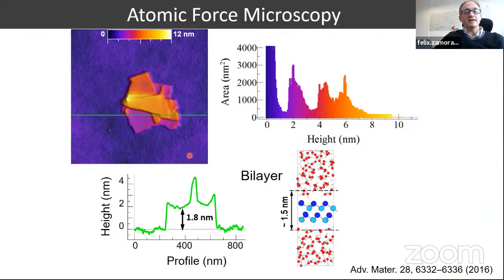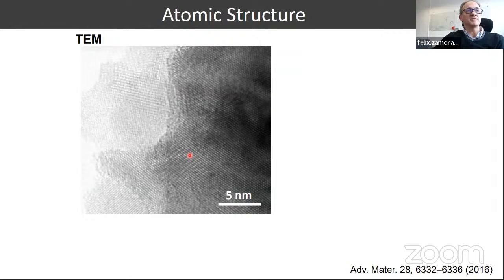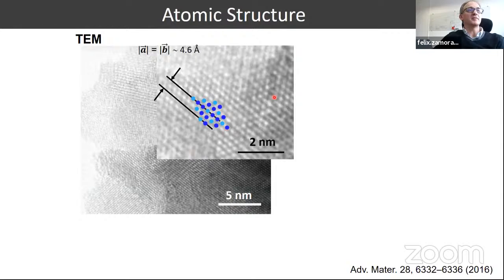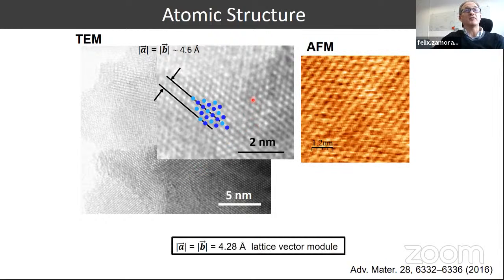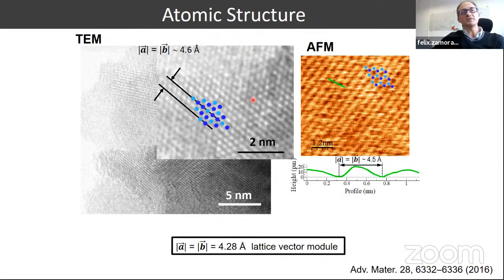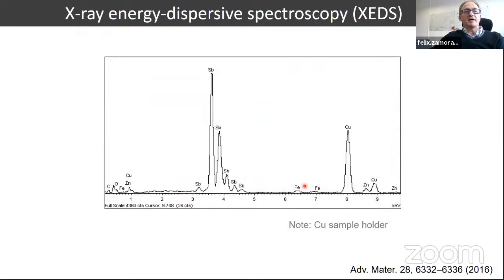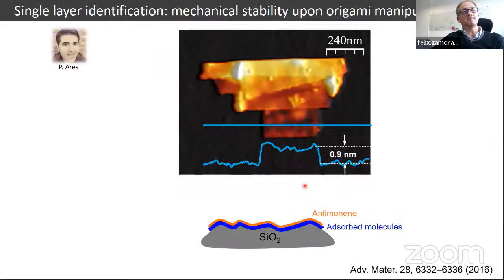Additional characterization by transmission electron microscopy shows that we retain the nice crystallinity, with atomic resolution. And here we have the expected parameters, confirming that we have beta antimony in these few layers of antimony. This was also confirmed by higher resolution atomic force microscopy, in which we can have atomic resolution and the same lattice parameters. This is just to confirm that we don't have any change in the composition, and using energy dispersive X-ray spectroscopy, we confirmed that we have just antimony as expected.